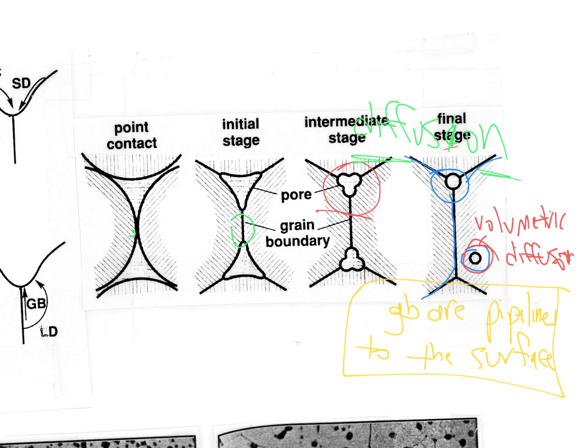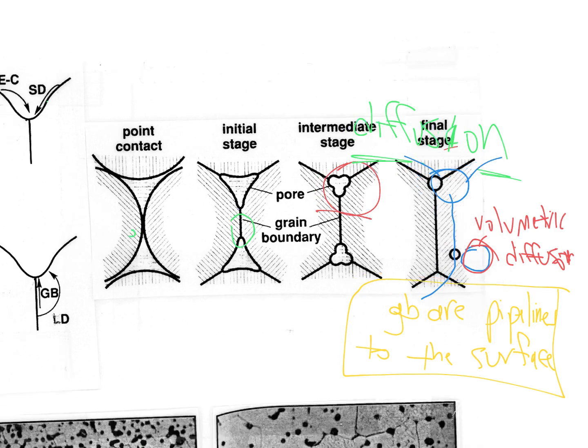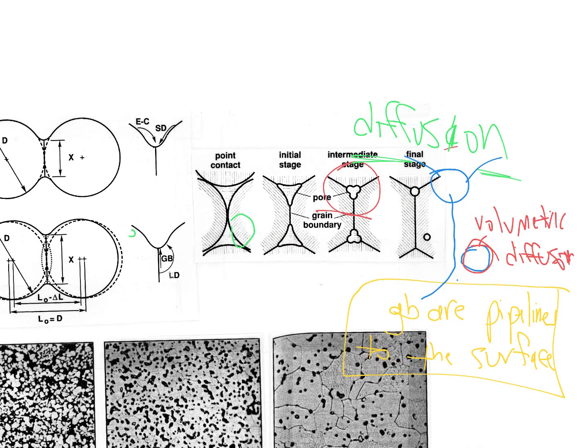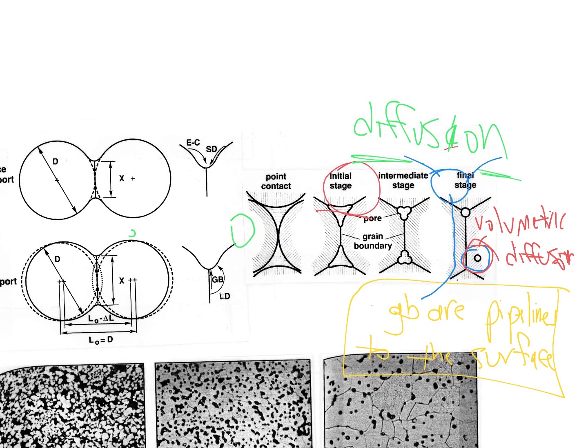All right, so if you recall, I showed you this image. We like the fact that it does that. That allows us to get these gas atoms out more quickly. And if a grain leaves a pore behind, in the middle there, we're stuck with this annoying volumetric diffusion, which we don't like. Very slow, very expensive, high temperatures, long times. Your boss is not happy. You're spending more money on energy costs than you should be. Okay, and so that is a big driving force for a lot of